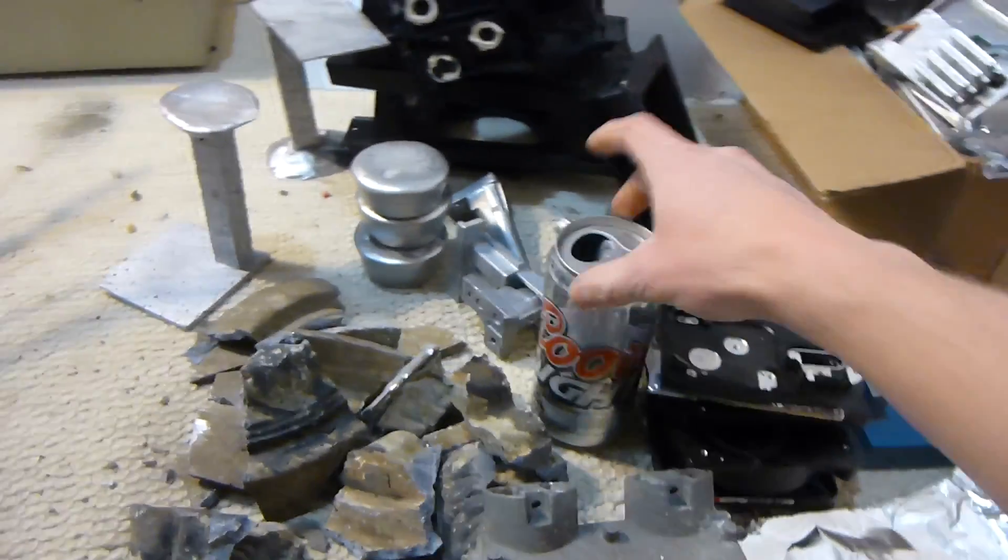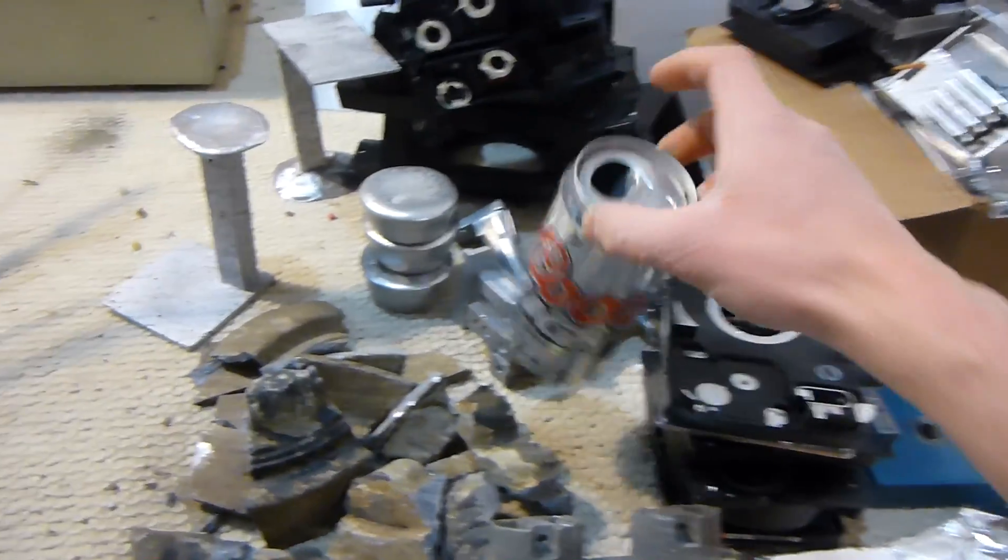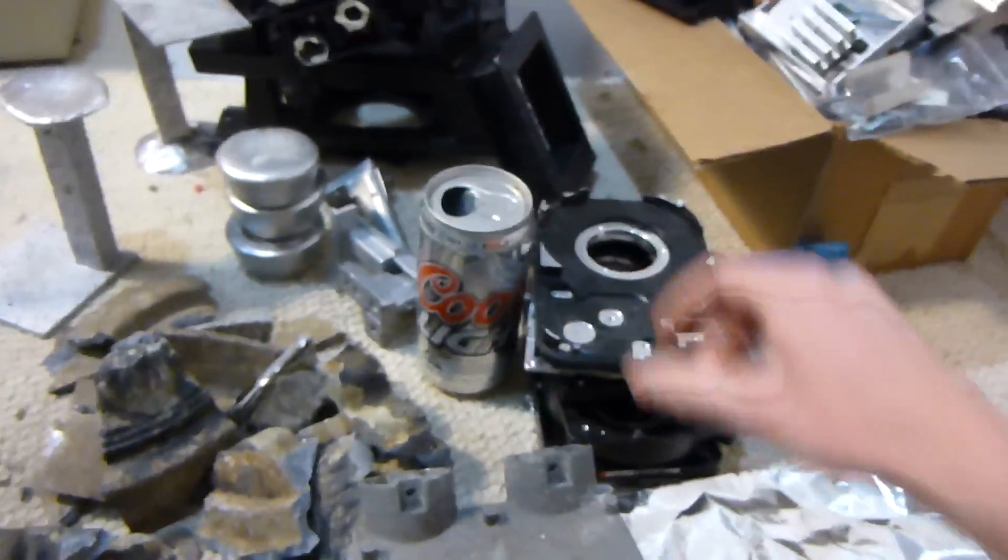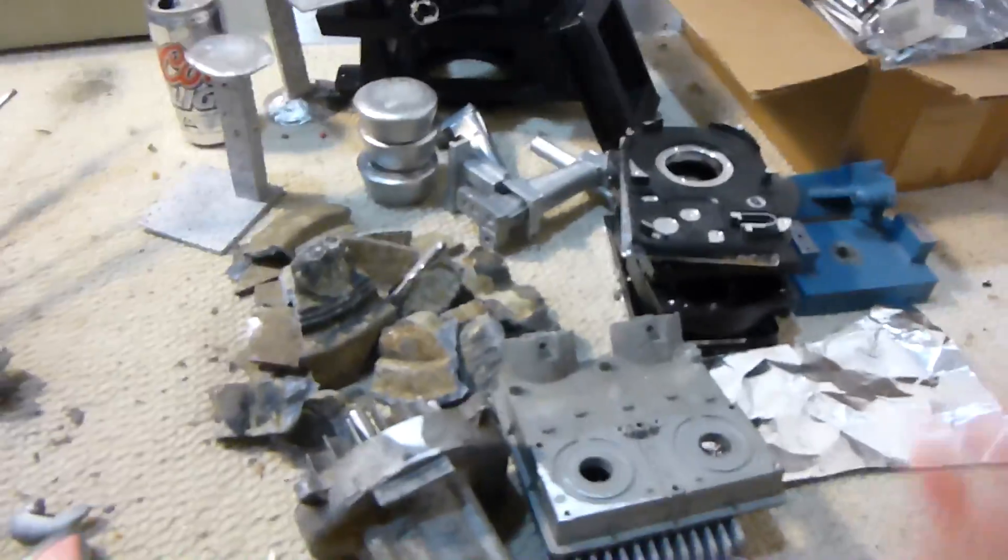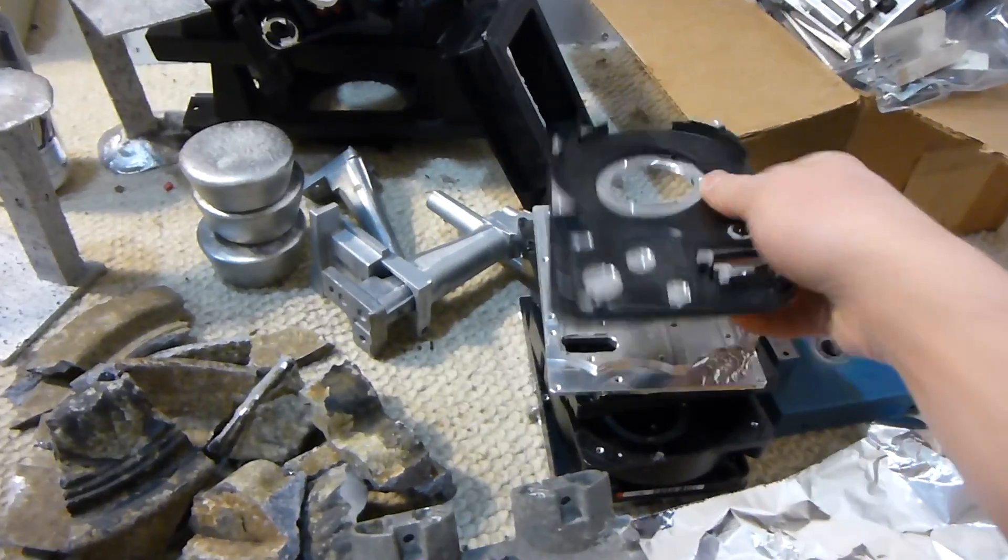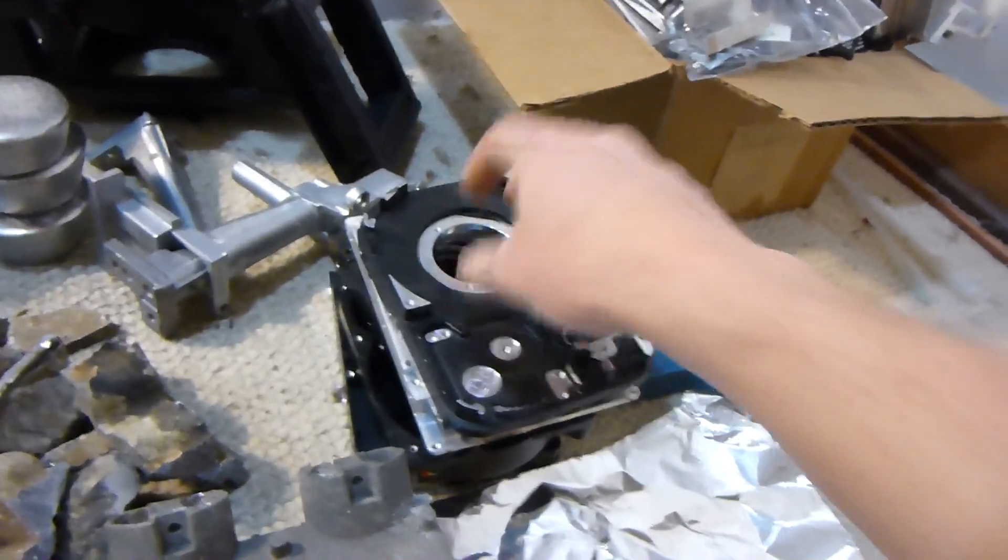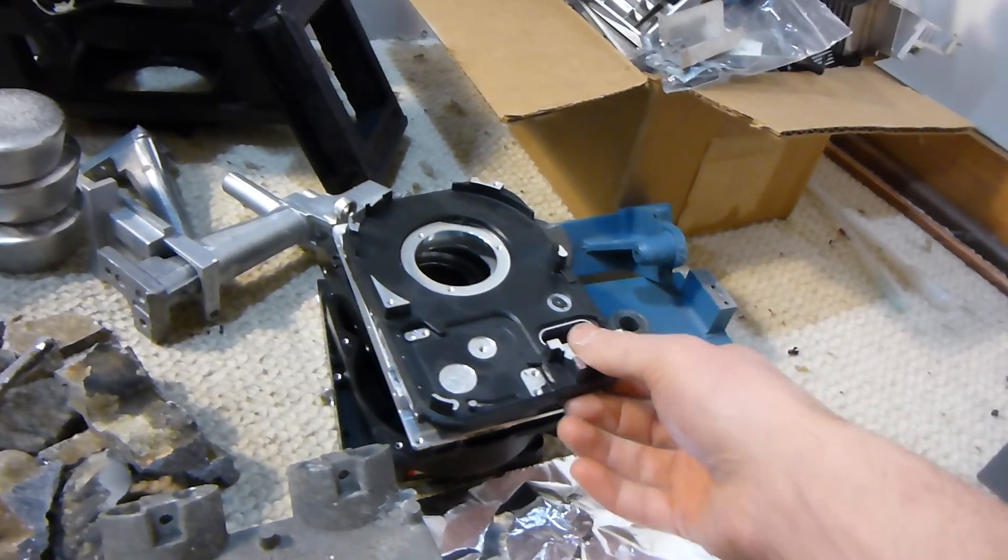You're going to find aluminum in drink cans. While it works well to use aluminum from drink cans to cast with, it's not the best quality. You also have to put like, for a pound you need like 50 cans at least, so you're going to be sitting there just feeding these things in forever. And you're going to get a lot of plastic and dross that you're going to have to skim off. So aluminum cans are good because they're free. Another good place is just taking things apart and getting like hard drive. This has got a lot of aluminum in it. The hard drive frame has a lot of aluminum. I like those a lot because especially if you're going to cast stuff, you especially want to find stuff that's already been casted because it already will have some flux. It's just the right alloy for casting. So I would recommend finding things that are already casted, such as these. These were from projection TVs that holds the lens.